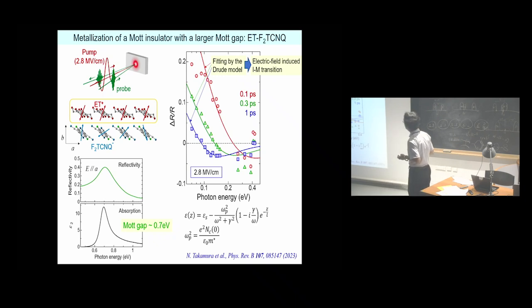The studied material is the Mott insulator ET-F2TCNQ mentioned before. The Mott gap is 0.7 eV, and by excitation with the terahertz pulse having an amplitude of 2.8 megavolts per centimeter, clear Drude responses are observed like this. This indicates that the electric-field-induced insulator-metal transition occurs. These results suggest that a terahertz pulse is a strong light source to generate carriers in semiconductors and insulators with a larger optical gap.